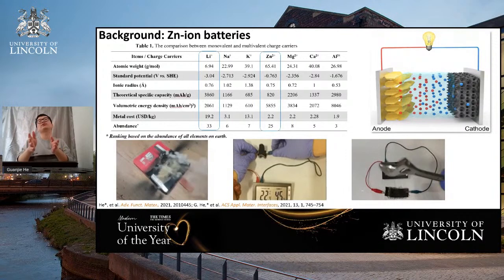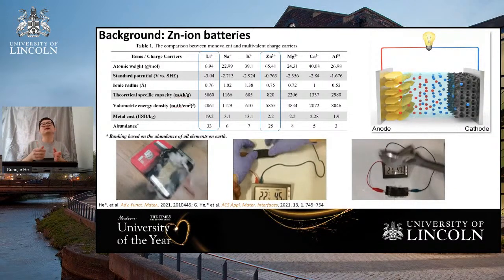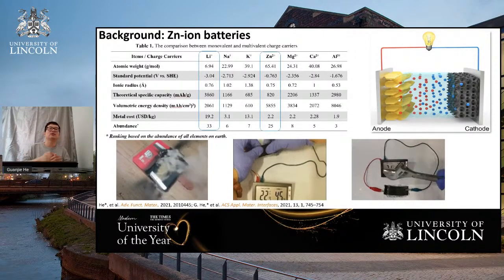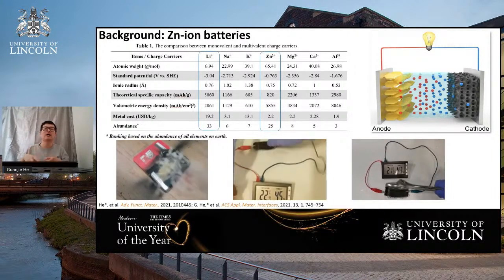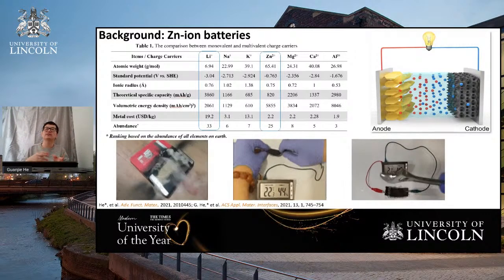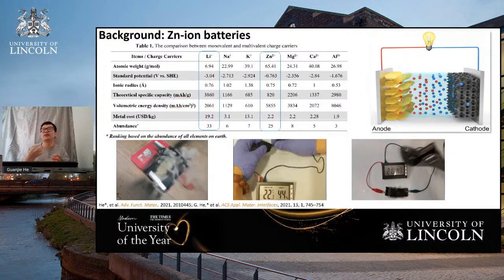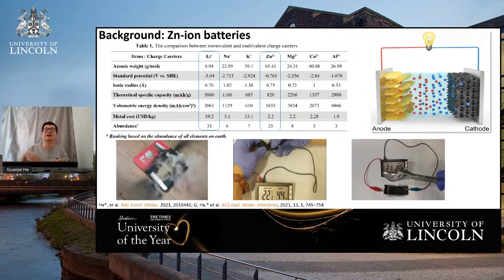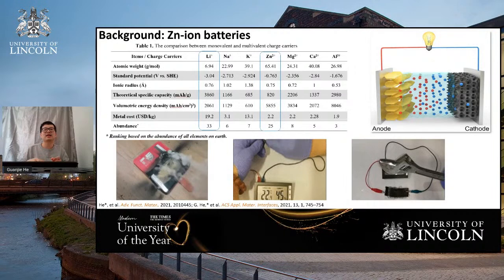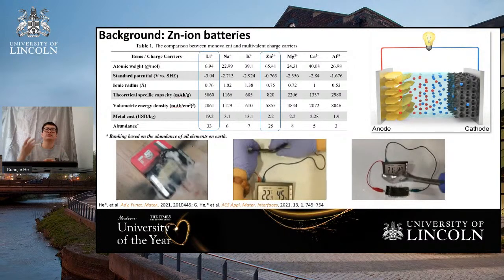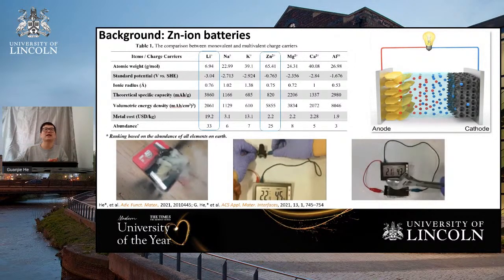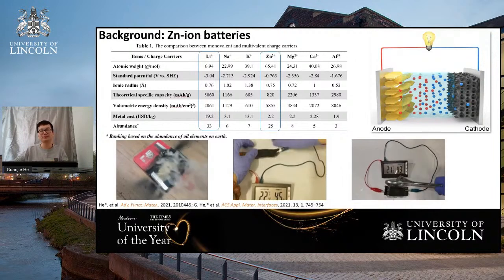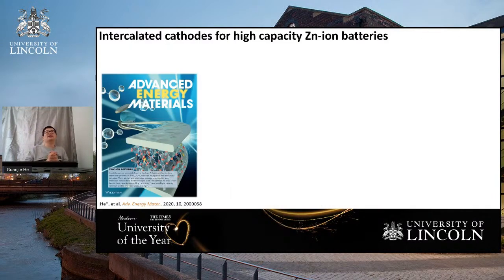And due to the high atomic weight of the zinc, and also there's a 2 electron charge transfer. If we use the aqueous electrolytes, there might be some problems related to like the polarization, and the hydrated zinc ions is relatively large, not like the ionic radius as shown here. And we try to develop the suitable cathode materials. This is one of the major research direction in my group.